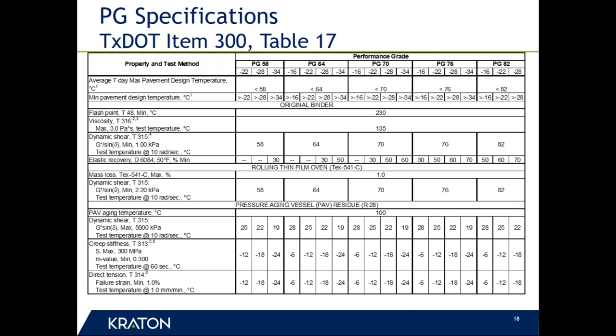This is the Texas DOT current specification out of Item 300, Table 17, and you can see a suite of different grades ranging from PG 58 to PG 82, and then low temperature grades going from minus 16 to minus 34. I was referring to 64 minus 22 before, and so you can follow that along in there, and that would be right here if you can see the cursor, by just going right down through there to see the properties. What this does is define testing temperatures, and the criteria that I've mentioned before are over here.